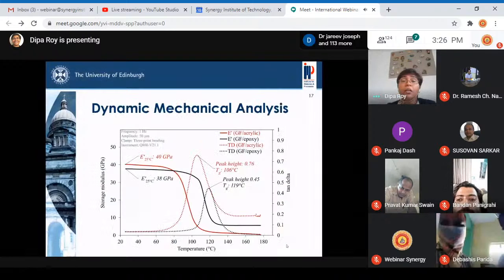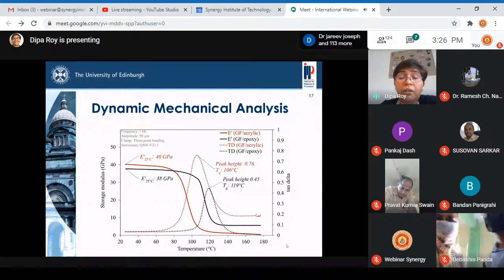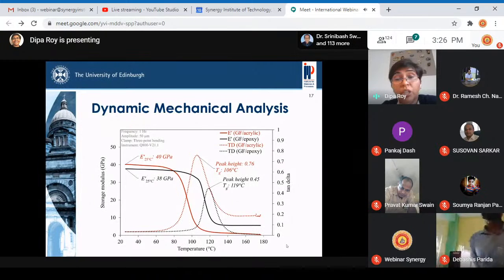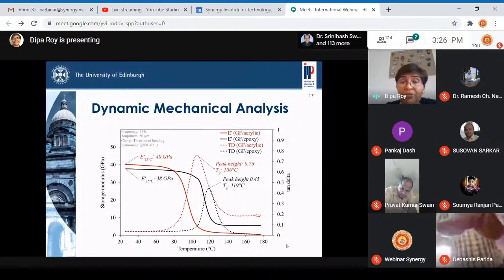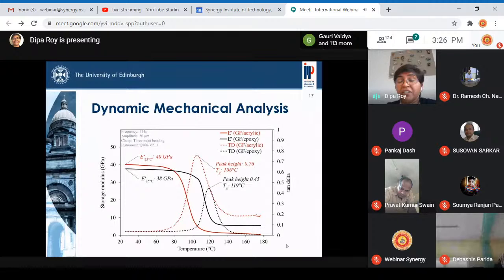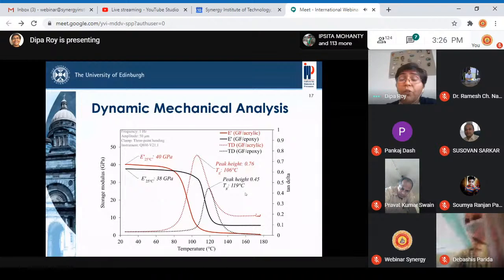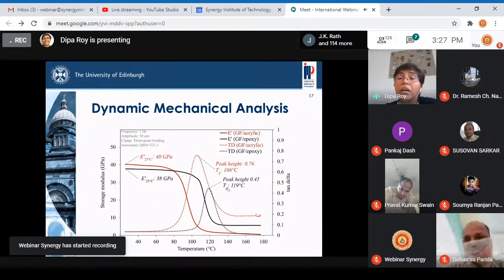Now we measured the glass transition temperature of both composites. We tried to select an epoxy matrix which is quite close, because we know epoxy resins can have a Tg from 50 or 60 degrees up to 180 degrees. So we tried to select a grade of epoxy quite close to the acrylic resin. The glass transition was about 119 degrees for the epoxy, and for the acrylic it was 106 degrees. So they are pretty close.